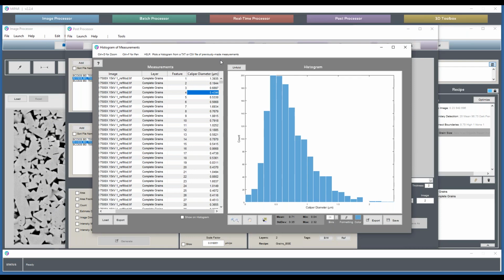They were able to use backscattered imaging in the SEM. That takes roughly 50 seconds per image. They were able to do 240 samples in 1 day instead of 4 months. And that saved their SEM operational cost. That saved them roughly $575,000 in SEM operational cost. So that is this case.